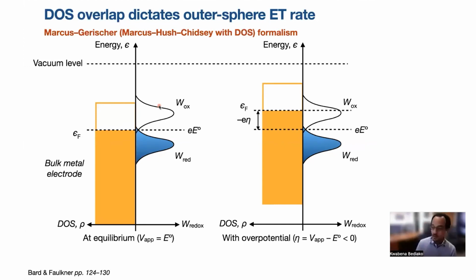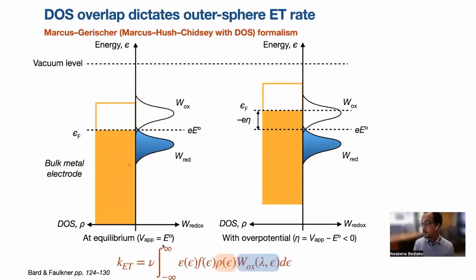And as I was saying, more recent studies suggest that we need to go beyond the Butler-Volmer model. And these types of considerations of density of states may be warranted even for transition metal surfaces where you have the bands from d orbitals that are highly non-dispersive, where they play a key role in the interfacial charge transfer. So this model tells us that the rate constant for our reaction is some function of the density of states of the electrode and the probability distribution function of the molecules in solution.